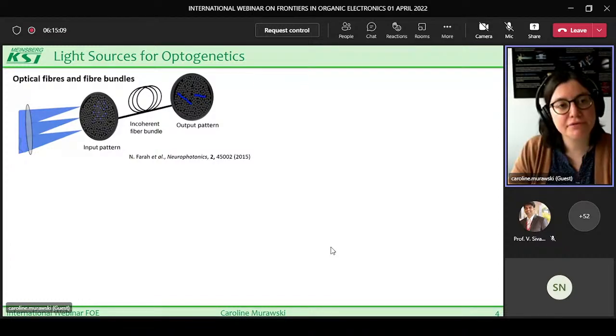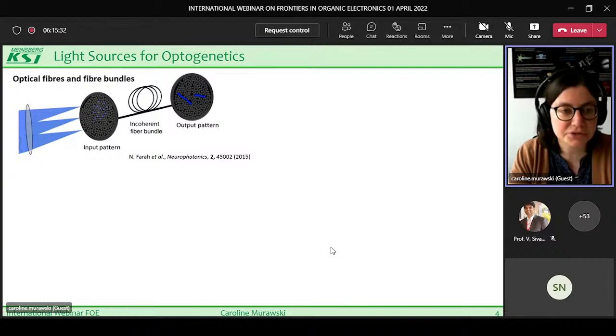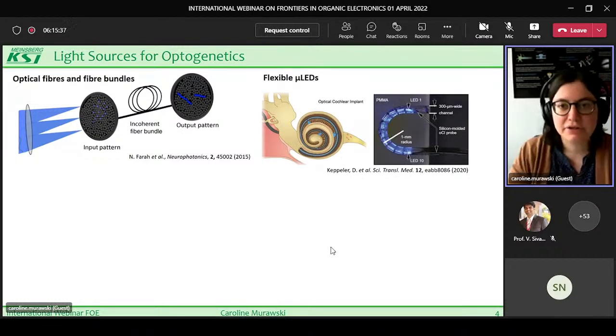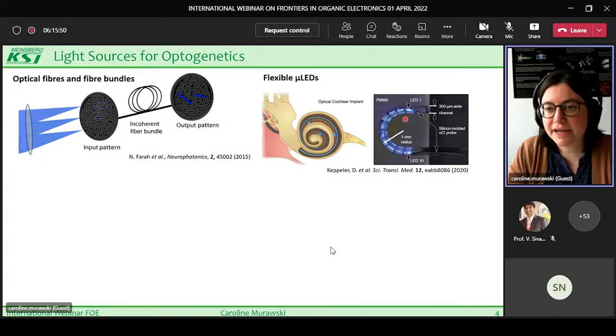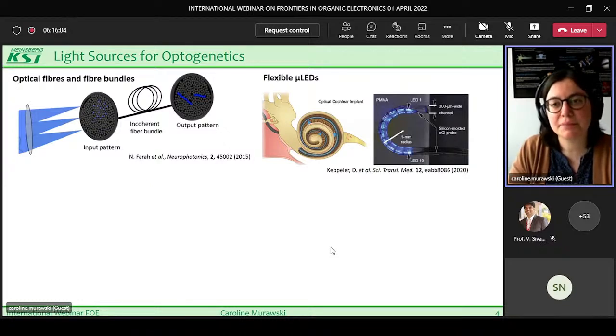The most prominent light sources used for optogenetics so far are optical fibers that in a more advanced fashion can also come in fiber bundles, so one can get a little bit of spatial resolution. Still pretty much limited, and of course the optical fibers are rigid. It's not very convenient to attach them to a brain in a mouse, for example. And alternatives that have now come up are flexible micro LEDs, as have been used, for example, in such an optical cochlear implant. But if we look at the overall structure, we have here approximately 1 millimeter bending radius. The whole system is 300 micrometers thick, and of course LEDs themselves are usually not flexible, so one can just create such demonstrators by picking individual LEDs and placing them at a relatively large distance in order to gain some flexibility.